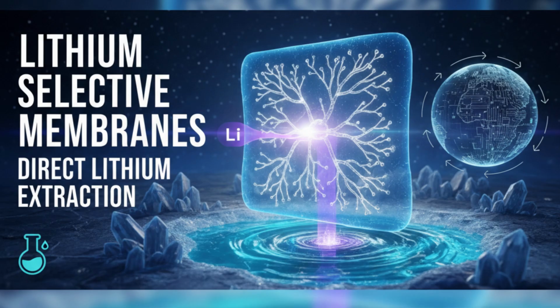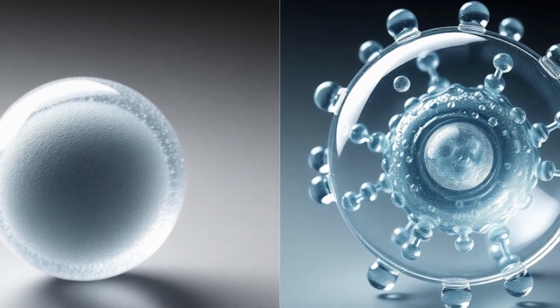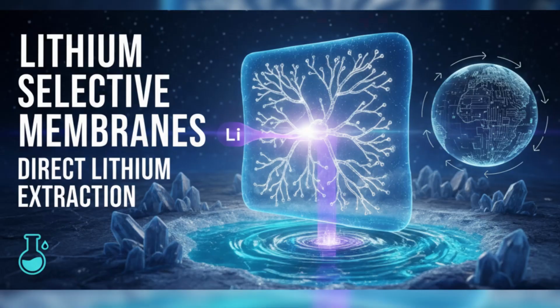If only. See, the complication is hydration. In water, ions attract water molecules. They wear a sort of hydration shell, or as you put it earlier, a winter coat. And because lithium has such a high charge density packed into that tiny size, it holds onto water molecules really tightly. It actually attracts a larger hydration shell than the others. The paradox. The smallest bare ion ends up being the biggest one once it's dressed in water molecules. Precisely. So Li+ ends up with a hydrated ionic radius of about 0.382 nanometers. Compare that to sodium at 0.358 nanometers or potassium at 0.331 nanometers. It's actually the largest of the three when hydrated.